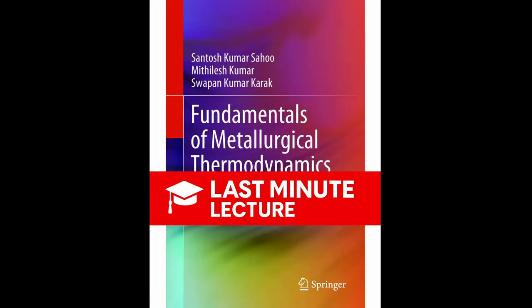The derivation is really elegant. It starts with the definition of G and that partial derivative we already found. At constant P, dG/dT equals minus S. We substitute that minus S into the definition G equals H minus TS, and with a bit of algebraic manipulation involving the quotient rule, we arrive at the core relationship. The partial of G over T with respect to 1 over T at constant P equals H. And for a chemical reaction, it's even more useful. Yes. The partial of delta G over T with respect to 1 over T at constant P equals delta H.